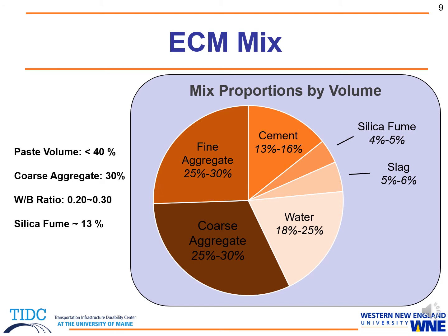and this is to reduce shrinkage in our concrete. So within our paste volume, cement is right around 13 to 16%. Silica fume is 4 to 5%, slag is 5 to 6%. Those are again by volume.